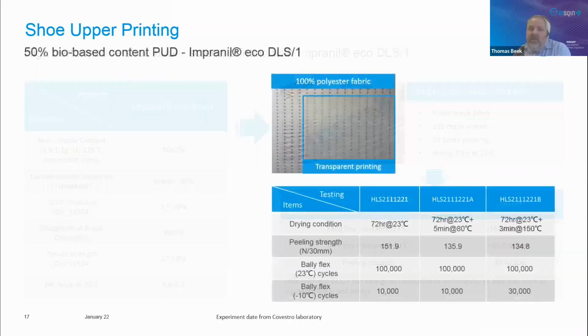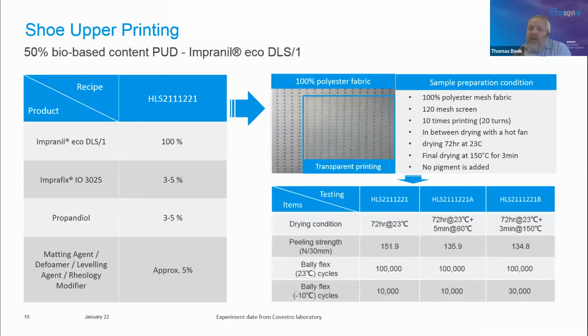Next slide, please, Thomas. In this slide, you can see a trial. We had mainly a trial where we ran on similar products like before, but we used here in this recipe also the Imprafix IO 3025, which is an aliphatic isocyanate, and it enhances the cross-linking effect. As well, we use propanediol, a leveling agent, a deformer and a rheology improver. This time we used a 100% polyester mesh fabric, again a 120 mesh screen, and like in the previous trials, we printed 10 times.